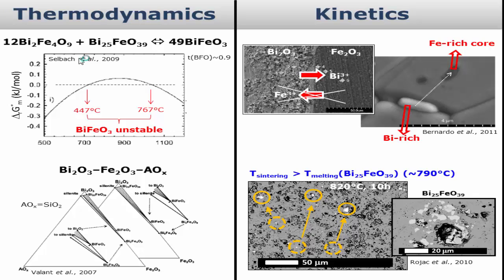So I will talk about two things. One is thermodynamics with phase diagrams, and the other is kinetics. When you work with BiFeO3 and think you have a binary system between bismuth and iron oxide, it is almost never the case, because you almost always have a third or fourth component, which is your impurity, and I will show an example with silicon oxide. Then there is kinetics. We are working with solid-state reactions, which work on diffusion, and very often some of these secondary phases may be stabilized just because the diffusion is incomplete at a certain temperature.